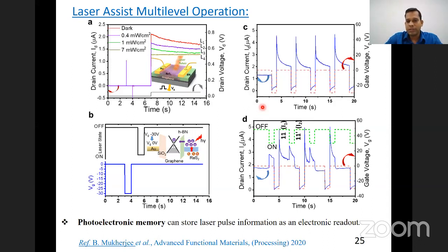And from this figure, we can clearly distinguish 3 different erase states. The first one is without light, so we have only the 1 and 0 states. But later on, once we use the laser pulse, we can have different erase states, basically 1, 1 and 1, 1 prime. So from here, you can clearly visualize that it can be used for multi-level operation.